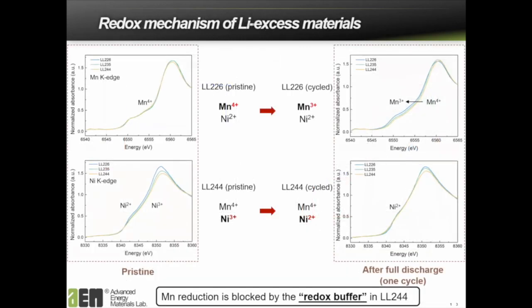Finally, we wanted to verify whether this redox buffer concept really worked in suppressing the voltage decay. So the investigation of oxidation states of each sample clearly shows that the original sample with the manganese 4+ and nickel 2+ produces mainly manganese 3+ after the multiple cycles. And then we know that this actually caused the decay of the voltage. On the other hand, the sample with the redox buffer showed that even after the cycles, manganese 3+ is not produced. Instead, nickel was reduced from 3+ to 2+ to compensate for any kind of changes in the structure, serving as the redox buffer.